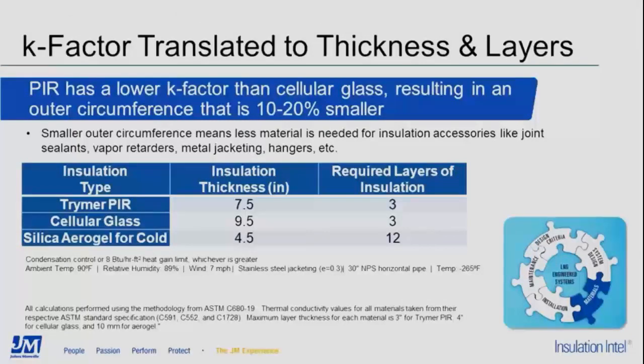Sure, no problem. Silica aerogel has a thermal conductivity that's roughly half, remember lower is better, roughly half that of Trymer PIR, which will result in a thickness requirement of roughly half. You can see the thickness here of 7.5 versus 4.5 for Trymer PIR and aerogel. The aerogel is a little more than half here, but it's in the ballpark of half. So the total thickness of aerogel is going to be roughly half that of PIR. PIR can be installed in each layer at up to 3 inches of thickness, whereas aerogel can only be installed at 10 millimeters of thickness per layer, a little bit less than half an inch.